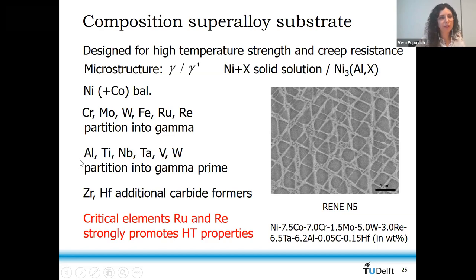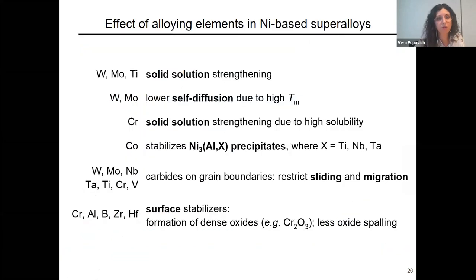So in Inconel 718, for example, you will have a gamma prime as Ni3Nb. So it depends on the alloying elements that they used. All the different elements are a cookbook that was added for a specific purpose. So partitioning to gamma prime; zirconium and hafnium are carbide formers. And lately what we see, as already mentioned, is rare earth elements such as rhenium, which have been used to strongly promote high temperature properties in nickel-based superalloys. This is just a summary for you, and I have a question from someone.